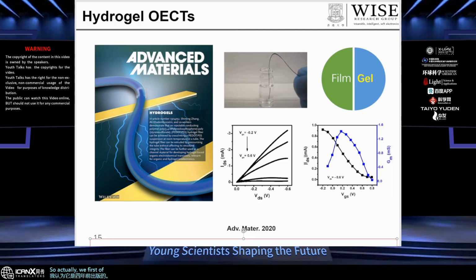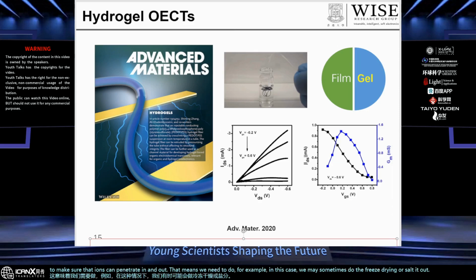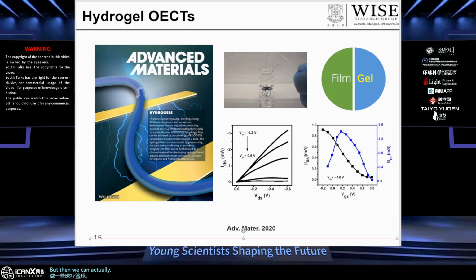First of all, it's called a multi-network hydrogel. Here we have the conducting polymer PEDOT:PSS, which is the active material of most OECTs, so we use this semiconducting polymer. What we can do is first form a PEDOT:PSS hydrogel layer. But in that case, we need some topological control to make sure that ions can penetrate in and out. That means we may sometimes do freeze drying or salt it out to make some micro holes.